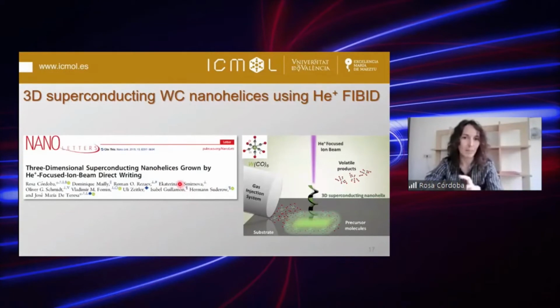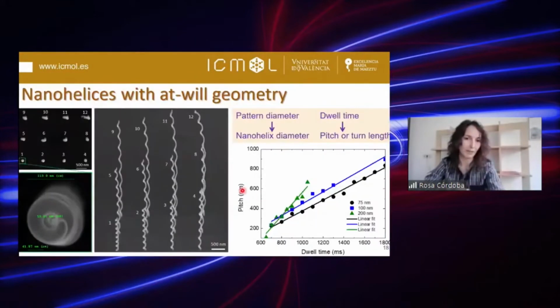Let's move to the second example on the 3D nanosuperconductors, and it's the fabrication of tungsten carbon nanohelices using the helium beam. And in this case, we are just modifying the beam scanning to create this kind of nanohelices. You can see here some examples. The diameter of the nanohelix was around 100 nanometers. And just by modifying the pattern diameter, we can tune the nanohelix diameter, and by modifying the dwell time, which is the time at which the beam stays in each position, we can modify the length of the turn of each nanospiral, as you can see here.